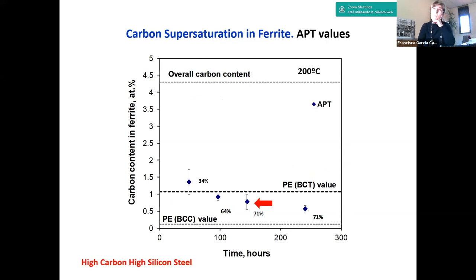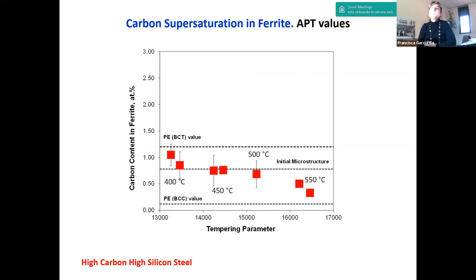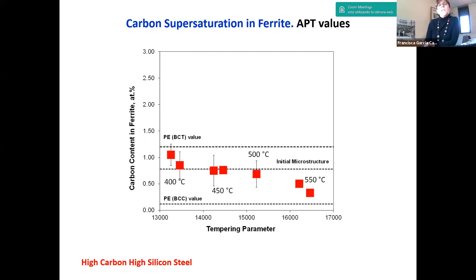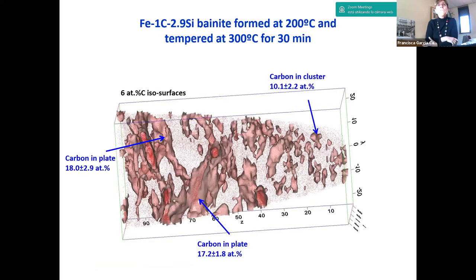Those values are for the very beginning of this journey to the atomic world, and that's with concentration profiles and proxigrams, but you can see the carbon supersaturation anyway, and the persistence with time that we check with tetragonality by synchrotron. And this is the tempering of one of those structures of bainite, and you can see that we need a lot of extra heat to start to see the evolution of the structure and to reduce the carbon supersaturation. But eventually we'll go that path of approaching equilibrium, and you can see how similar it is to martensite. This is low temperature bainite after tempering at 300 degrees C.